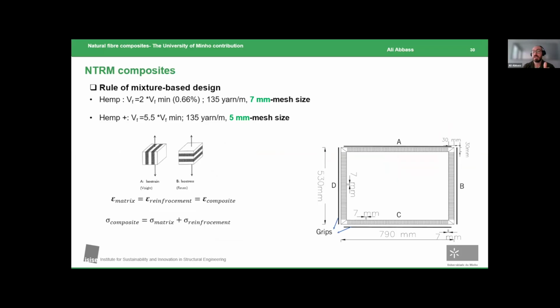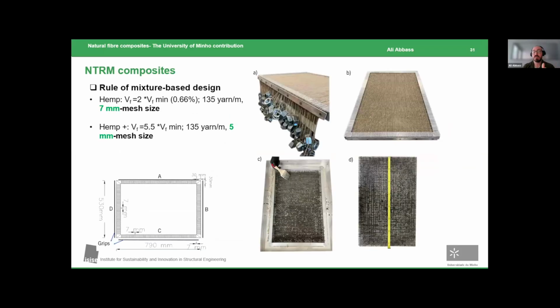Based on this, we designed a mold to cast the textile without weaving. Here you would see also the yarns are stretched by a constant load equal to more or less 2 or 3% of the tensile load capacity of the yarn. And then you would see the phases of coating, casting, coating, drying. Then we cut it into strips